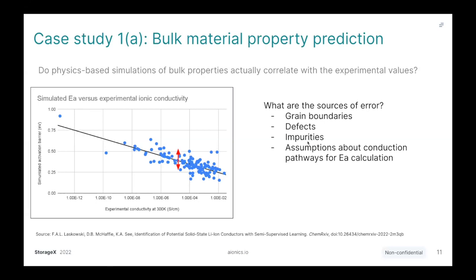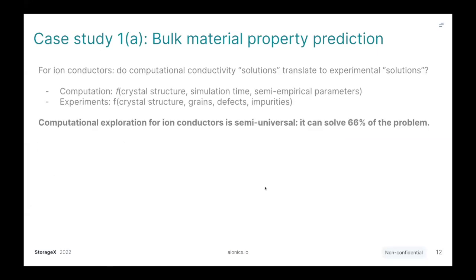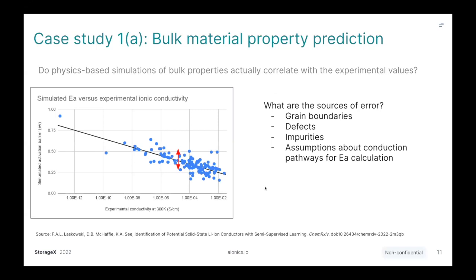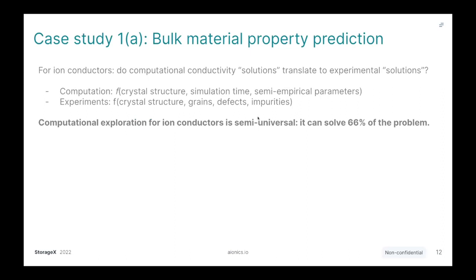And then with DFT, of course, you have semi-empirical parameters you have to worry about. You have thermostats, you have all of this stuff. You have simulation times. In this case, with the bond valence method, there can be assumptions about what the right conduction pathways are. So there are sources of error here, right? There are things that are not addressed between these two vastly different time and length scales. But from this data, I just ran a quick R-squared to see what this correlation actually looks like. R-squared is 0.66. So this would say that the computational method actually solves basically 66% of the problem, right? So that's pretty good. In this argument of maybe semi-universal, the answer is we can solve 66% of the problem across these scales.